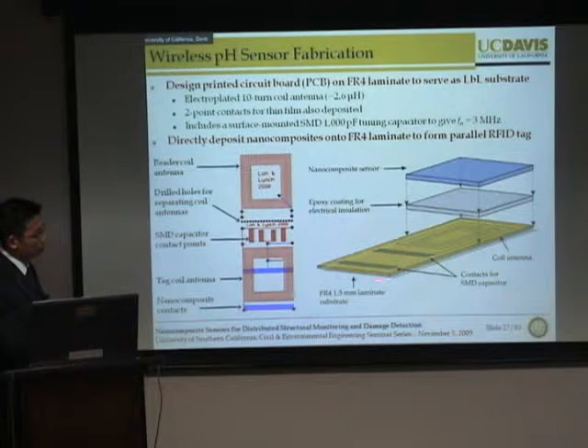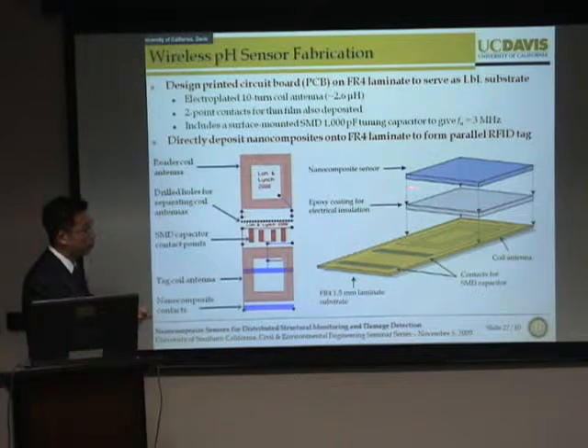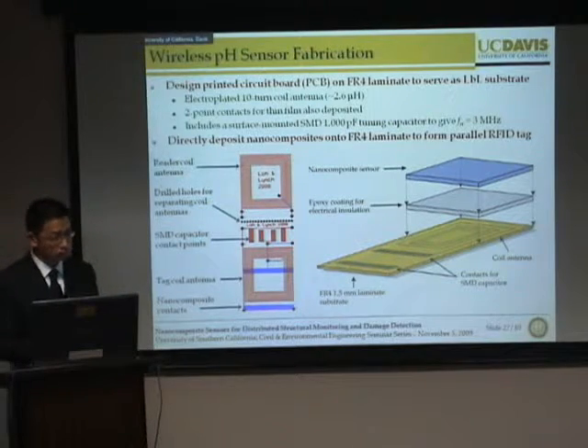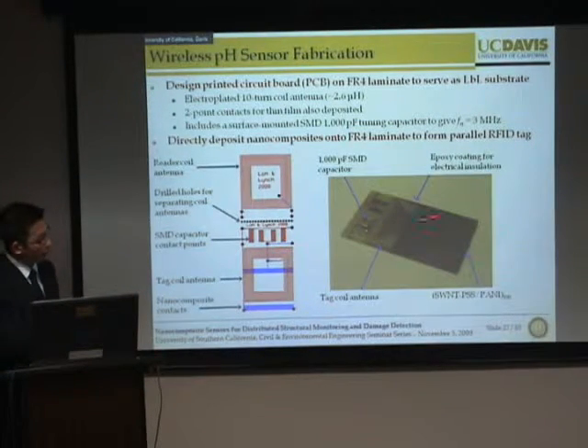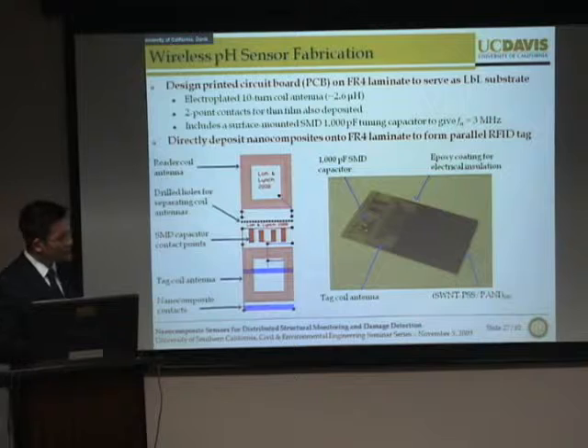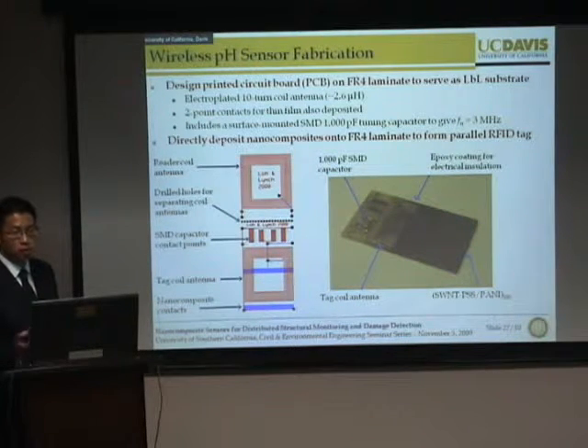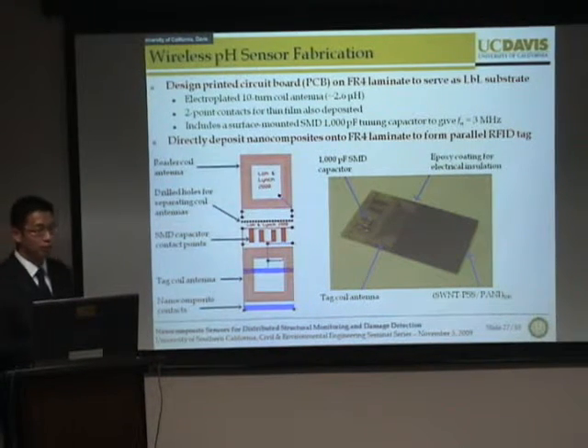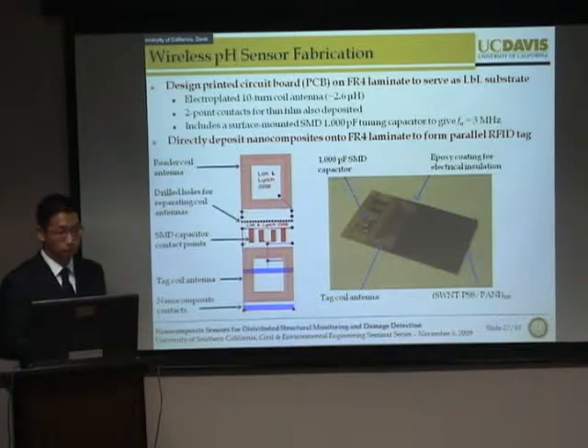So schematically shown here is how we can fabricate our thin film, where we can take your printed circuit board material, epoxy coat it for electrical insulation, and then dip it into your various solutions to deposit your nanocomposite sensor. Now, upon sensor fabrication, this is one of the prototypes that we have, and the sensor is about an inch by an inch, or 2.5 centimeters by 2.5 centimeters.